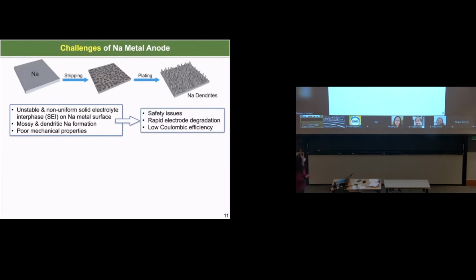So that's basically a summary of the issue I just mentioned. It causes a safety issue, and this can cause what we call rapid electrode degradation. Another big issue is what we call low Coulombic efficiency. What this means is that because sodium metal is highly reactive, once it interacts with the electrolyte, it can cause some parasitic reactions, so you can imagine that the energy you input into your battery doesn't really give energy. It actually transforms into some parasitic chemical reaction, so that leads us to what is called low Coulombic efficiency here.